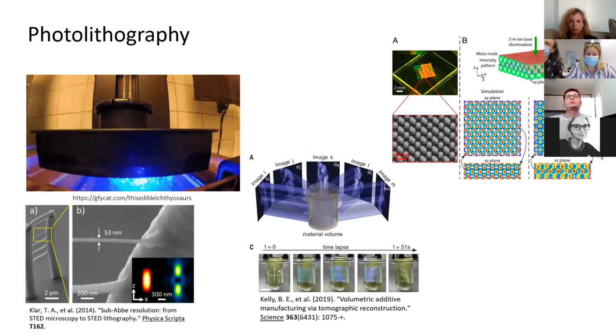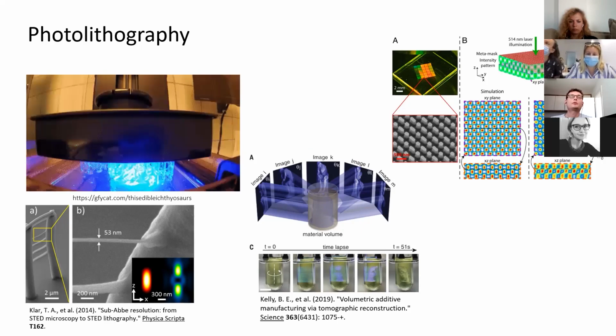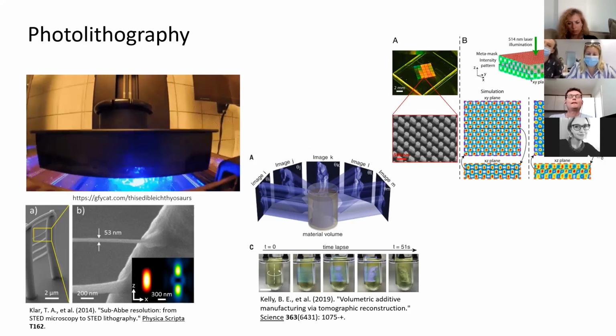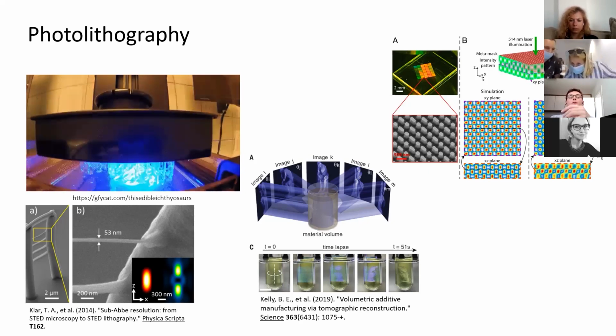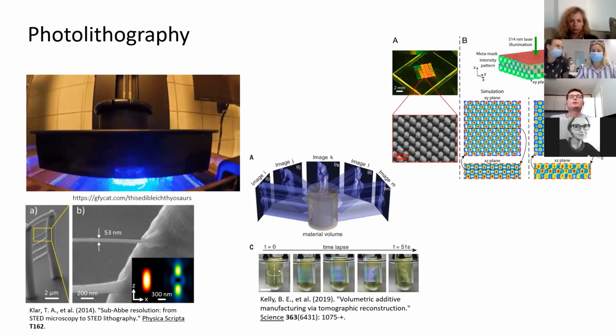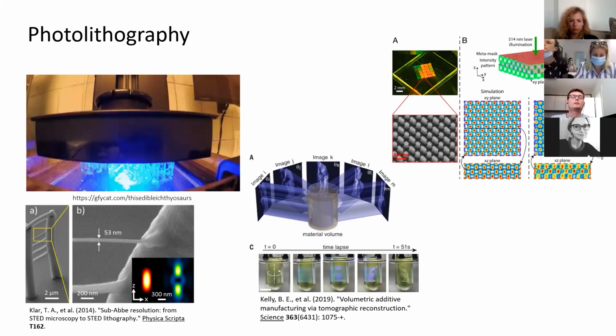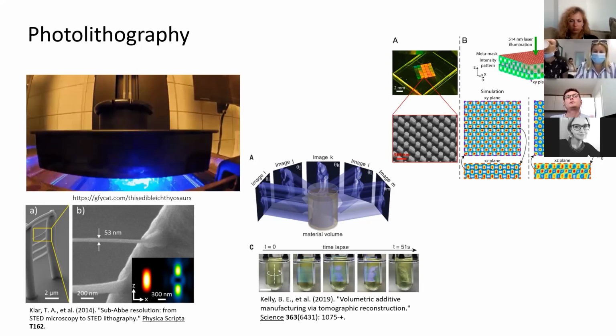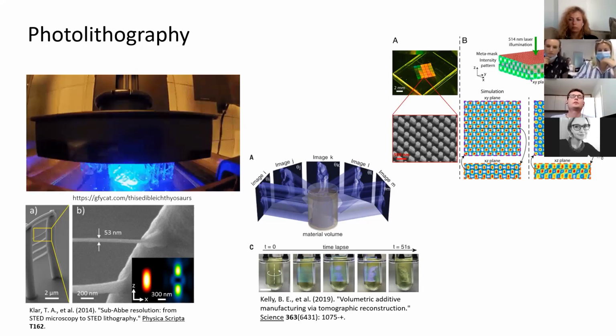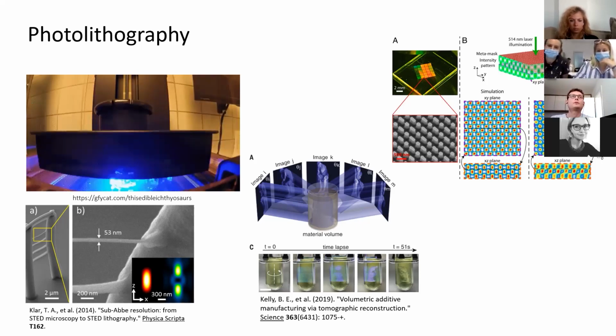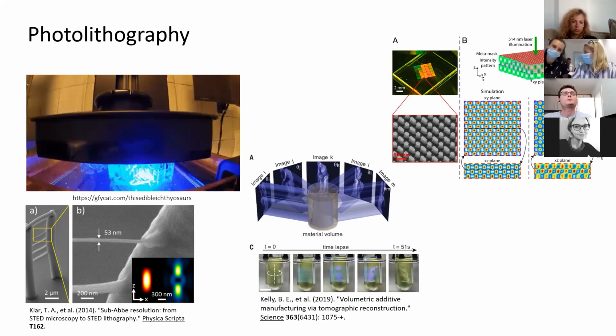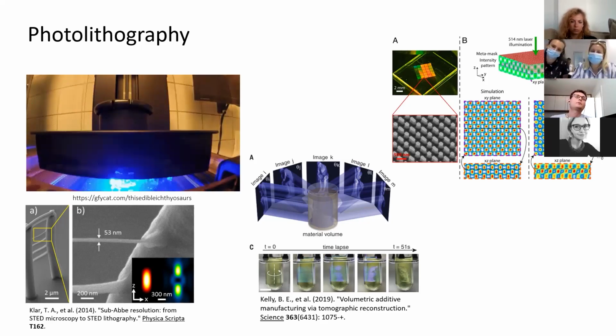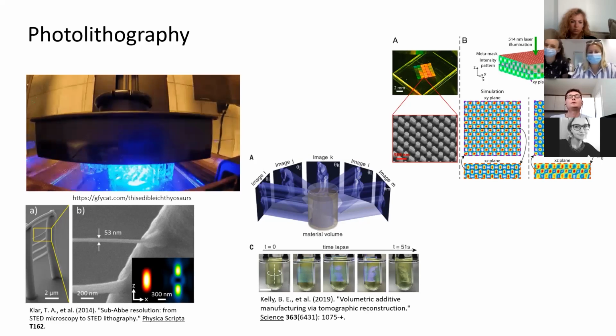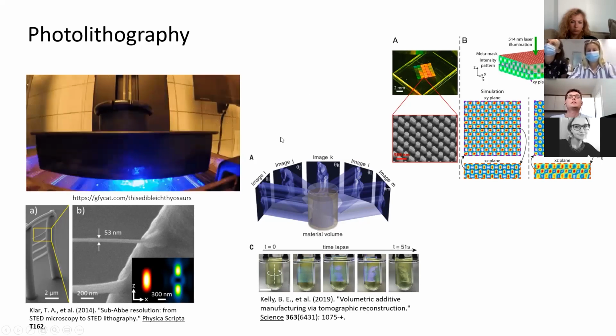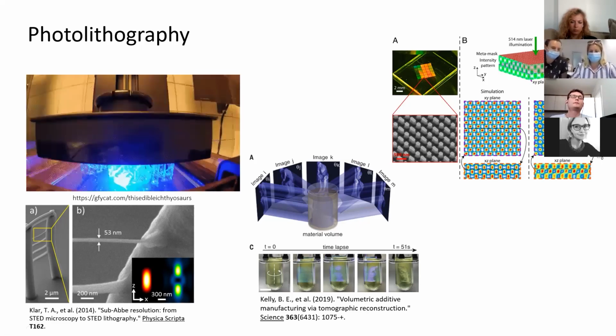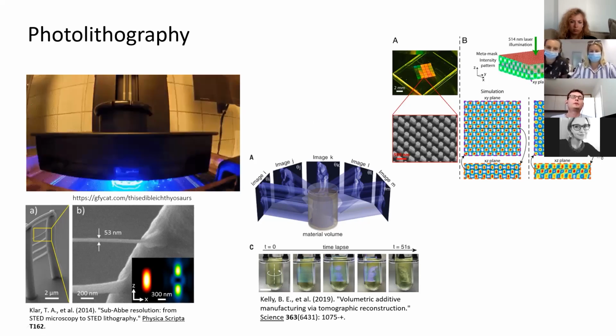This is also really interesting because it allows really high resolution and structuring of complex scaffolds. But it is limited in terms of the materials that can be used. Usually the photoinitiators, and even the monomers within the resin, can be toxic, and the degradation products of the scaffolds are also toxic. So there's a trade-off there, but with the development of new materials, this problem has been largely solved. On the other side, the main advantage of lithographic techniques like this is the high resolution. Standard SLA techniques are similar in resolution to droplet-based or extrusion techniques, in the range of maybe 50 to 100 microns.